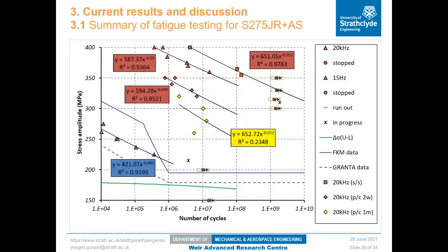This slide represents the summary of all obtained fatigue testing results. That's why I would like to stay on it a little bit longer. The first group that I would like to draw your attention to are the samples tested at 20 kHz. So maroon triangles are the samples where the crack originated from the surface, and maroon squares are the samples where the crack originated from the subsurface.